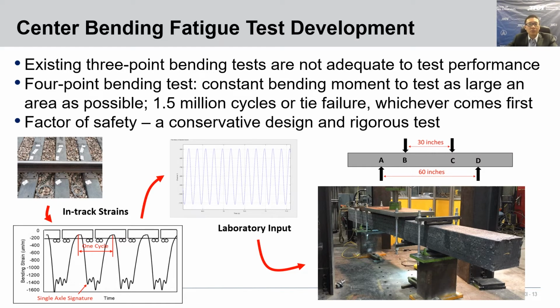This slide also shows the test setup on the top right. A 4-point bending test setup is used because it can provide a constant moment area to test the tie center area. And the section AD is a 60-inch outer span, which is consistent with the AREMA 3-point bending test. Section BC is the inner span, which is about 30 inches. Actually, we tested different lengths of inner span. A longer inner span is preferred because it can provide a longer constant moment area for tie testing.